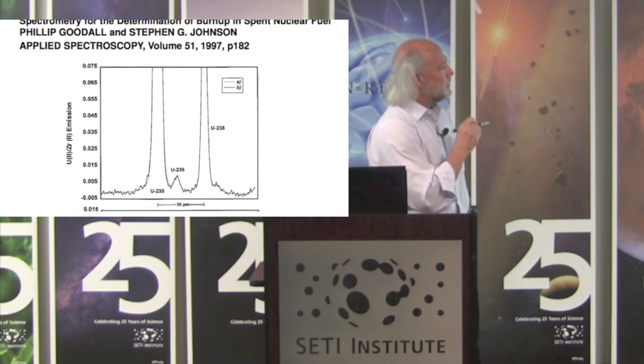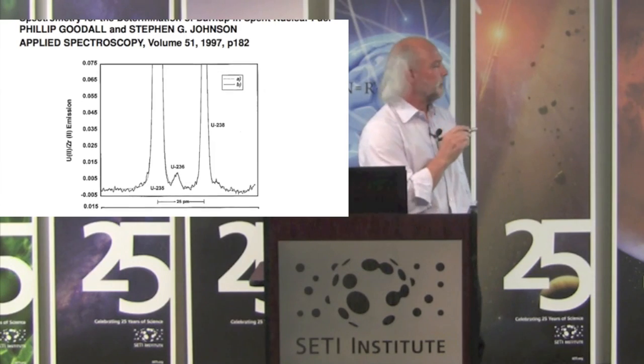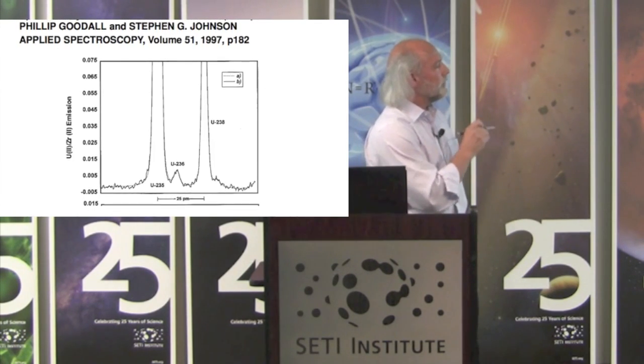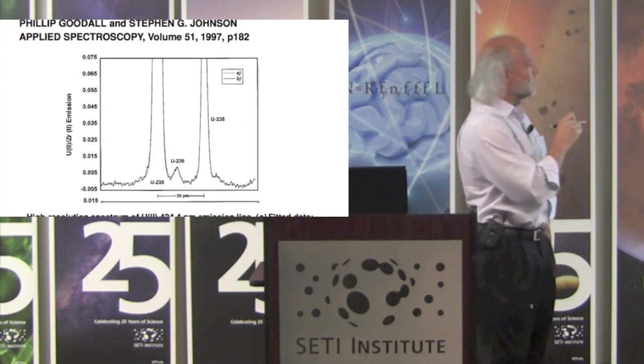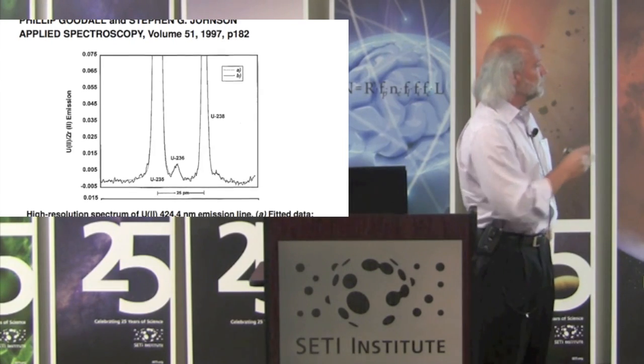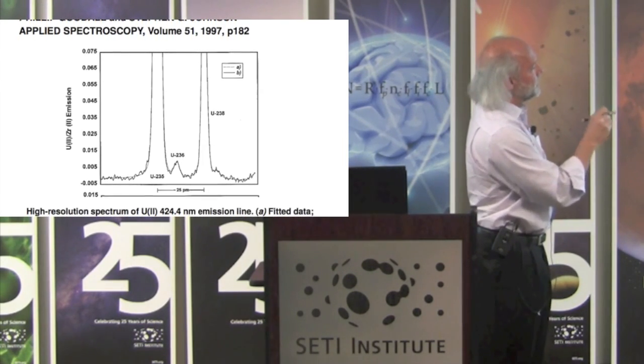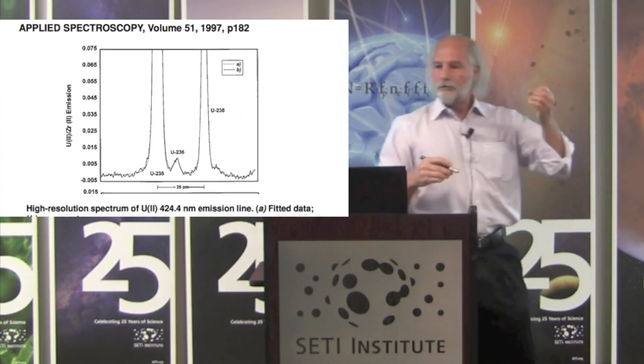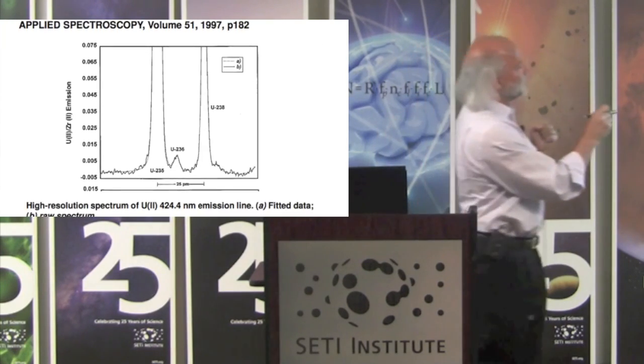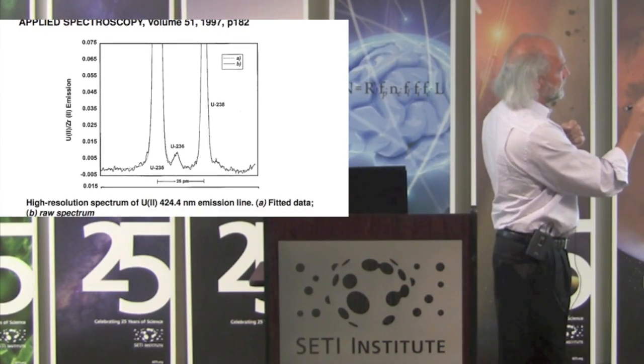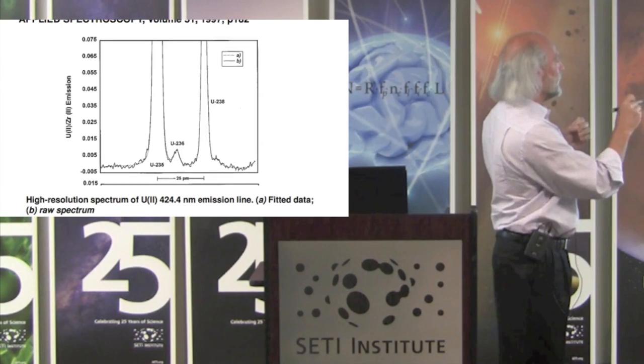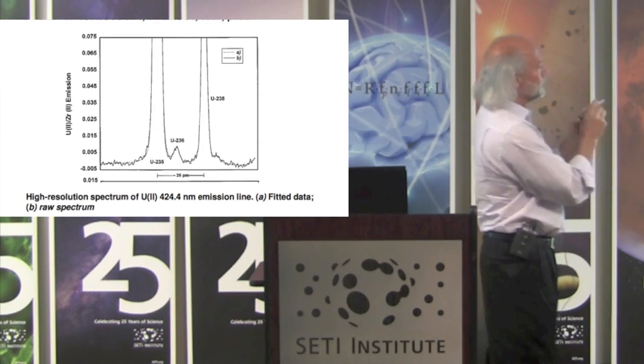But you can resolve this shift in an ICP OES if you have the right spectrometer. You have enough spectral resolution to see the 25 picometers. And when I was talking about lines being broadened, as the temperature increases or the electron number density increases, these lines will broaden, due to Stark broadening, mostly Stark, collisional broadening.